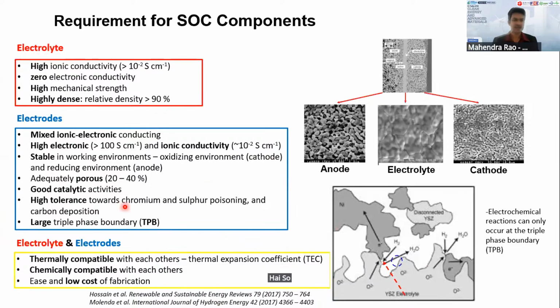So I just highlight a bit about the requirements. As we know, the electrolyte, the key requirement is the conductivity for the efficient ion conduction. For the traditional oxygen ion conducting, of course, we need high ionic conductivity. At any operating temperature, we need to make sure the ionic conductivity is sufficient for the operation of the fuel cell. And then the electrode, as we know, the electrode must have a good balance between the electronic and ionic conduction. So this is very important.